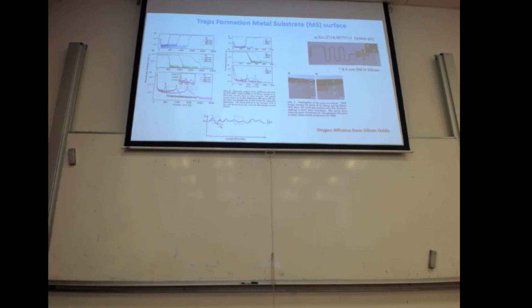So we are discussing what happens at the metal-air interface. Now let's move a little below and consider the metal-substrate surface. So we have the substrate and the metal. Basically, also there are traps, and the main reason is because there is oxygen. So I want to draw your attention to a very recent paper from the Chalmers group. What they were studying is transmons, with different thicknesses of aluminum, built on silicon.